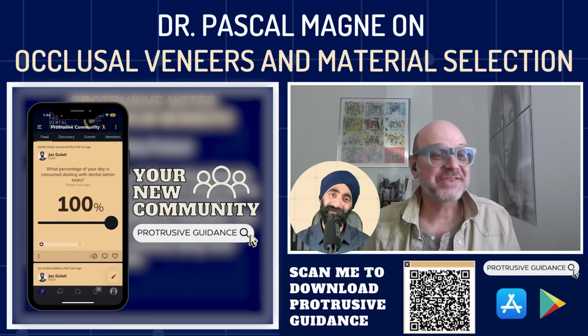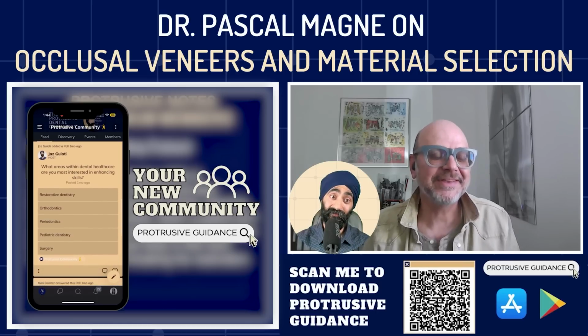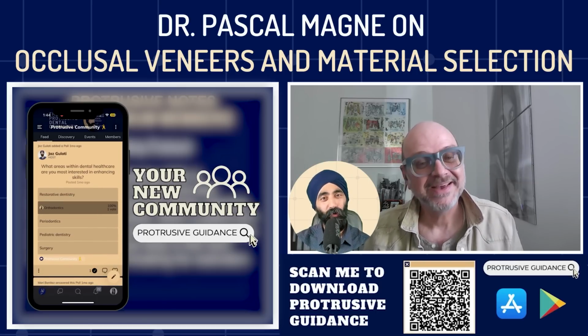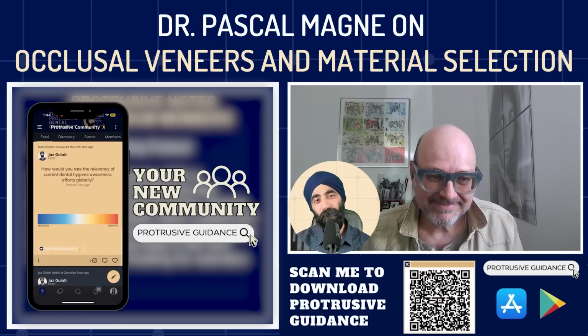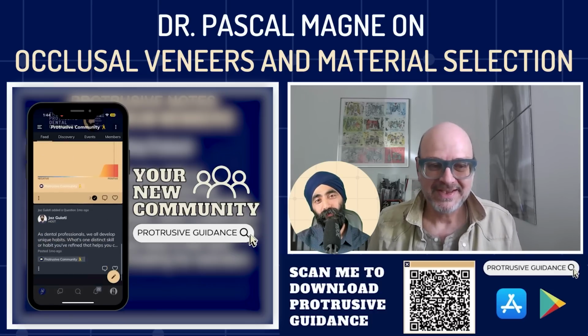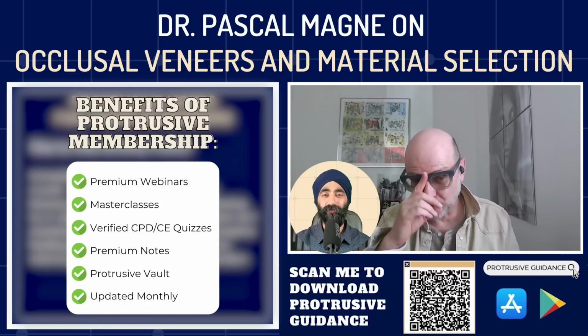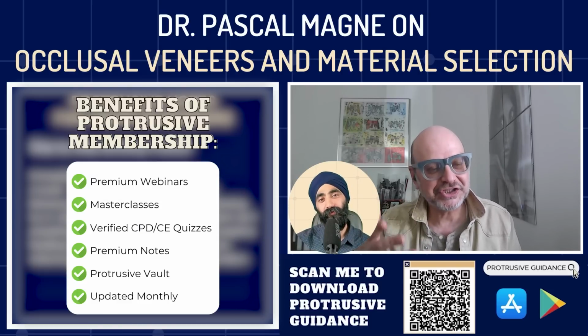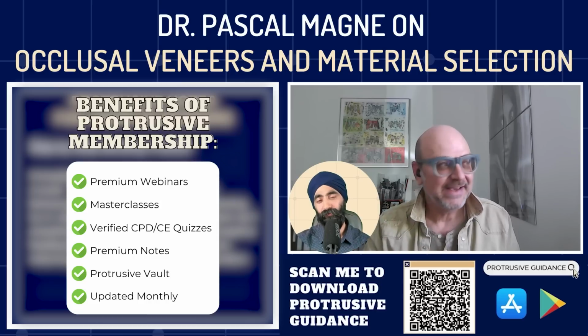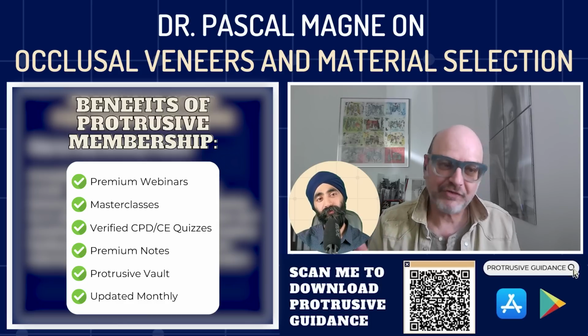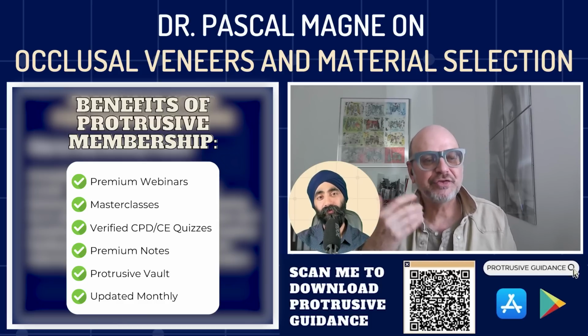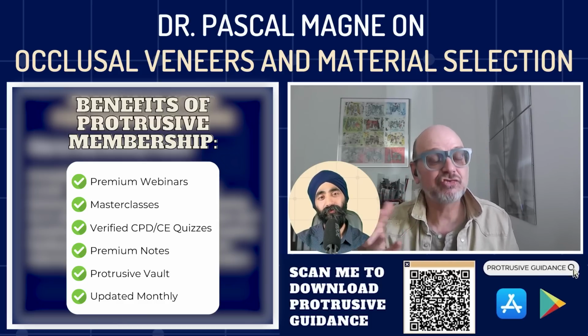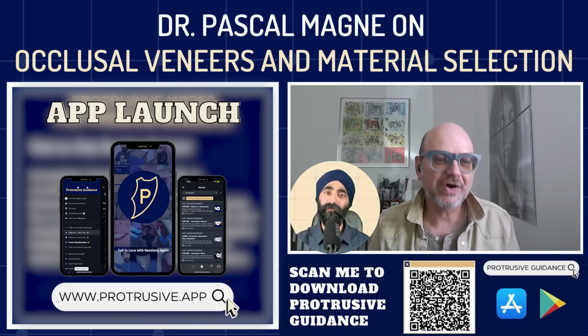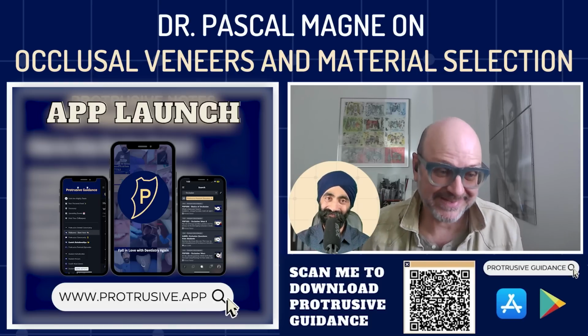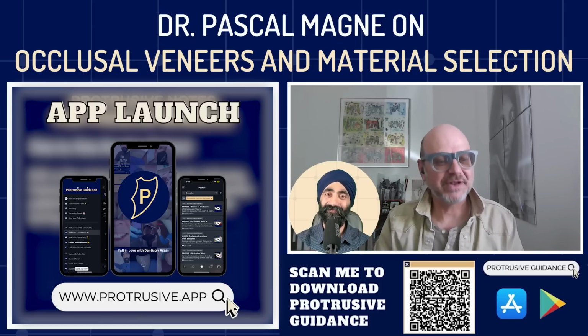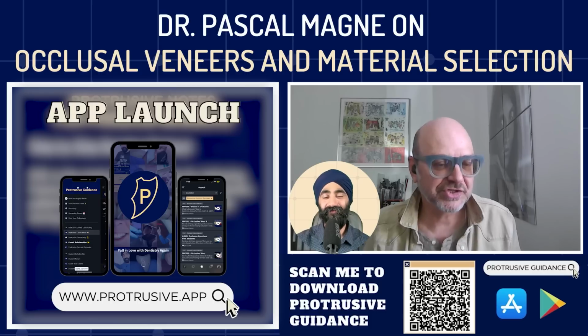One thing that will help you a lot is immediate dentin sealing. And do you know why? No, go for it. Because when you do IDS, the patient doesn't have sensitivity anymore. The dentin is sealed, is desensitized. So you can test your restoration without anesthesia. And if the patient is not anesthetized, as you know very well, the proprioceptive response is much higher. They will be less likely to bite strong when you test the occlusion. So IDS will actually be the most important element. You don't need to anesthetize, and your patient is much, much more sensitive to the occlusion and to the biting.